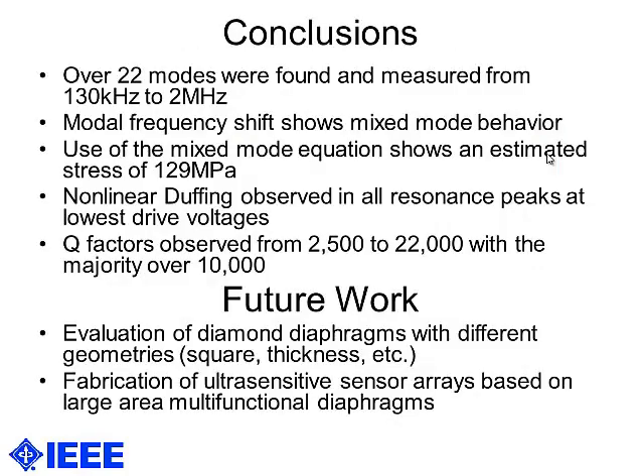So for this work, we observed over 22 modes and found them to range from 130 kilohertz to 2 megahertz. The mode frequency shift shows a mixed mode behavior due to the high Young's modulus and relatively low stress. Using the mixed mode equation, we get an estimated stress of 129 megapascals. Nonlinear Duffing was observed in all of the resonance peaks, even at the lowest drive voltages, and Q factors went from 2,500 to 22,000, with the majority of the peaks showing a Q factor over 10,000.